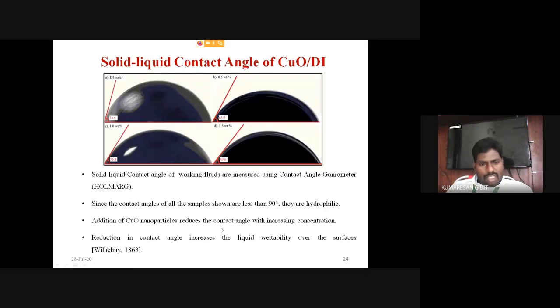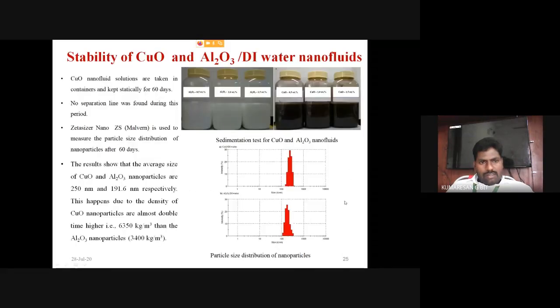Then addition of CuO nanoparticles reduces the contact angle with increasing concentration. Then reduction in contact angle increases the liquid wettability over the surfaces.